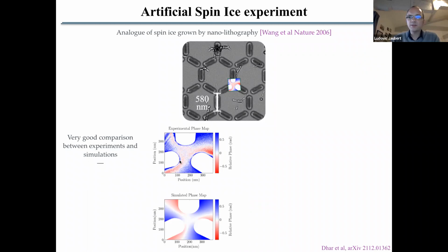So it's the same thing as what I was showing before. You put the sample of spin ice in the TEM, in the transmission electron microscope. You measure a difference of phase map in one case. You recombine them, you measure the interference, and that's what gives you the experimental phase map that you have here, that matches very well with the simulated one if you assume this length of permalloy.